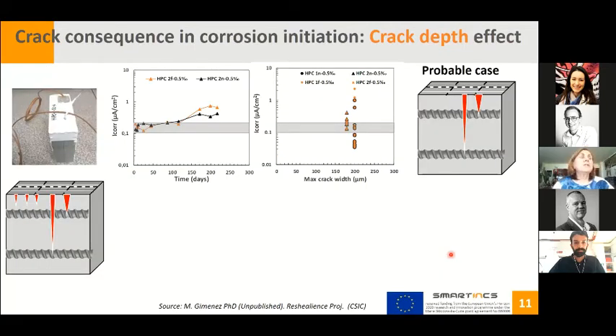But we have another aspect that we need to analyze in the corrosion initiation, that is the crack depth. This is the specimen exposed to the chloride environment, and the chlorides penetrate to reach the 2 levels of reinforcement. In this case, whether you are in the first or in the second, the corrosion has been initiated at practically the same time, and the crack is relatively high. So probably the situation that we have here is that the crack penetrates not only the first level of rebar, but also the second level of reinforcement.